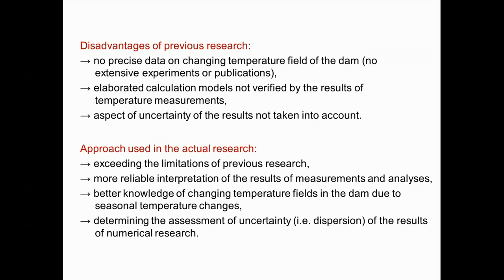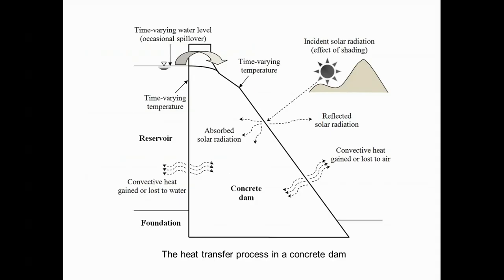Assessment of uncertainty of the results of numerical research was also determined. In a concrete dam there are different types of heat transfer. The time-varying temperature on the downstream side is influenced by absorption of solar radiation and by convection, while on the upstream side there is variable influence of convection due to oscillation of the water level. The thermal loading causes horizontal displacements at the top of the dam, which can be measured by pendulum.